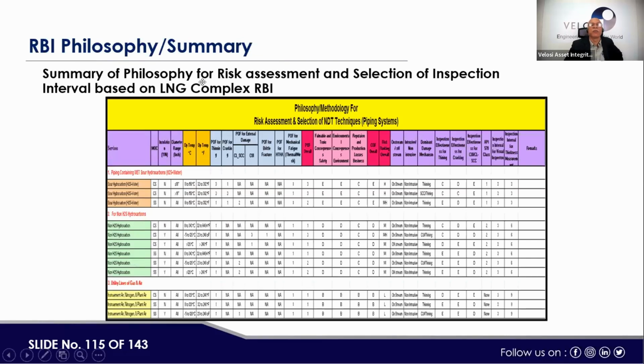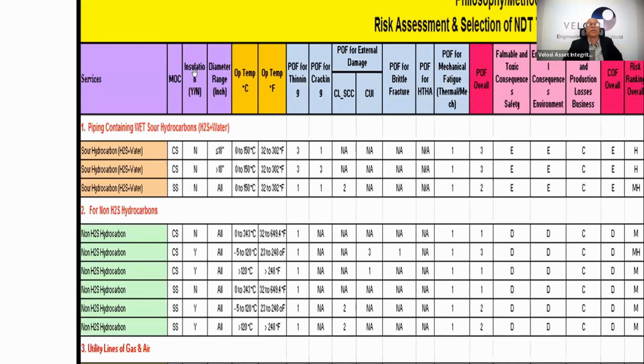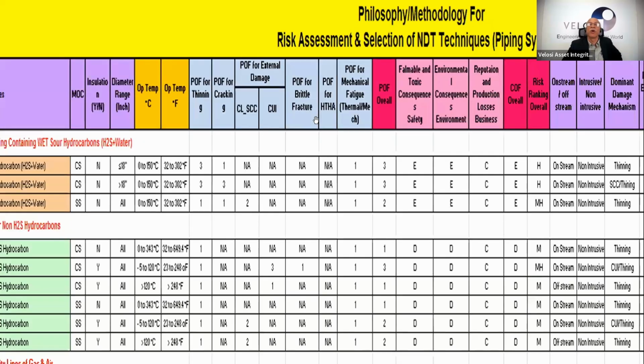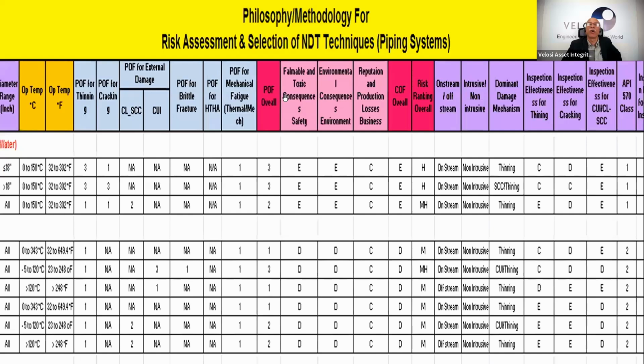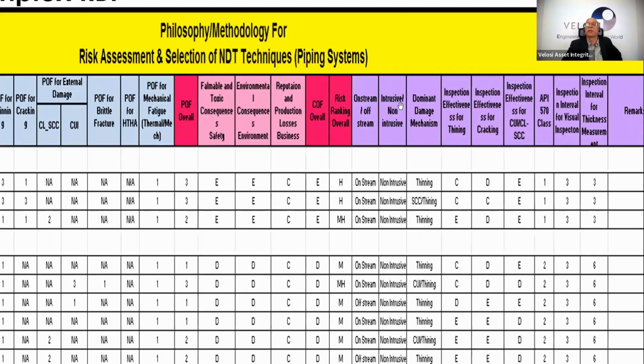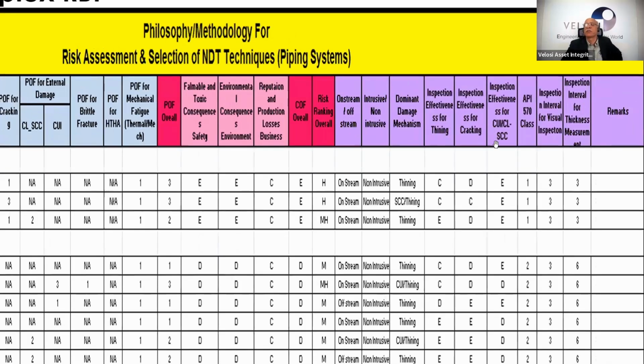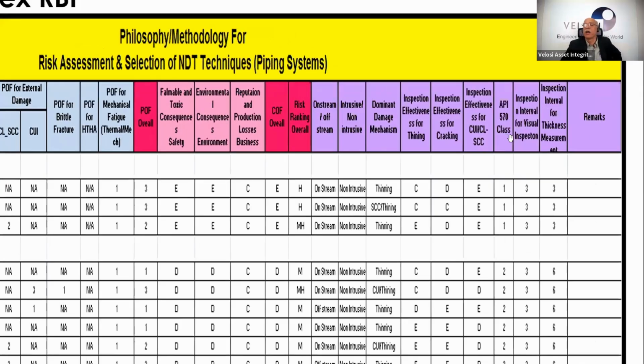So here is the summary of the philosophy of risk assessment and selection of inspection interval based on the LNG complex. So here we have the basis that we have used for the selection of the interval. Here, if you see the MOC, installation, diameter, operating temperature, operating temperature in Fahrenheit, POF thinning, POF cracking, POF external, POF brittle, POF HTHA, POF mechanical fatigue, then POF overall, then consequence wise, then on-stream inspection, on-stream, off-stream, or intrusive, non-intrusive, dominant damage mechanism, inspection effectiveness, then inspection effectiveness for SS, and then API 570 class, then inspection interval, and this way inspection techniques are further selected.